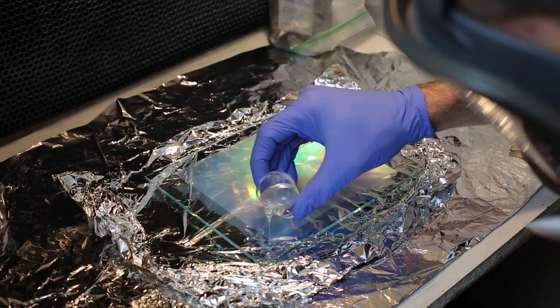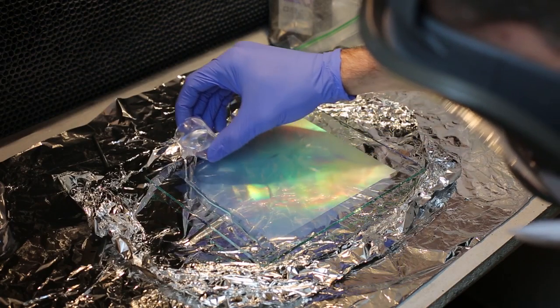The cover glass will be cleaned and dried in the same way I demonstrated before in my cleaning glass segment. I don't recommend gluing glasses of different thicknesses together, as this will decrease the longevity of the hologram. Glass of varying thicknesses will expand and contract in different ways and thus work against each other, weakening the epoxy bond over time. I pour the glue on the hologram.